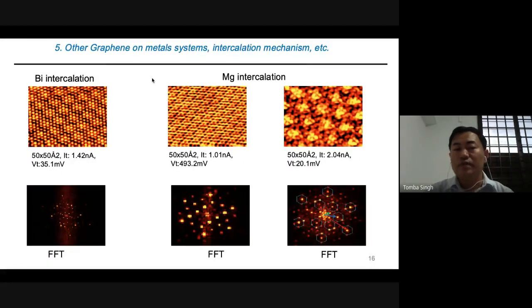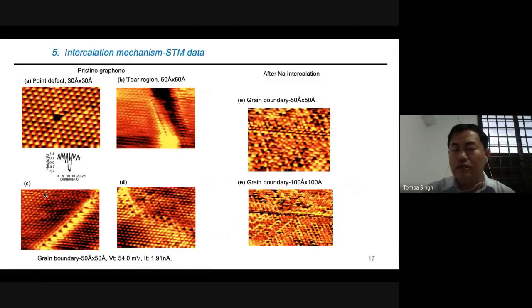I mentioned the Moiré pattern. We observe a nice Moiré pattern in the intercalated case. Here, this is bismuth intercalated graphene, and we see a nice Moiré pattern. A Moiré pattern is a periodic modulation of the surface. Not only the surface, there is also a periodic modulation of the electronic levels, the electronic structure. That's why it can affect the graphene electronic properties. In the magnesium case also, we observe nice Moiré patterns or superstructures. And the bottom ones are the FFT of the corresponding STM topography.